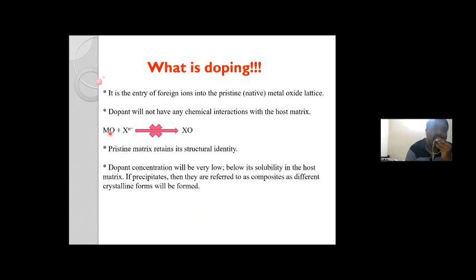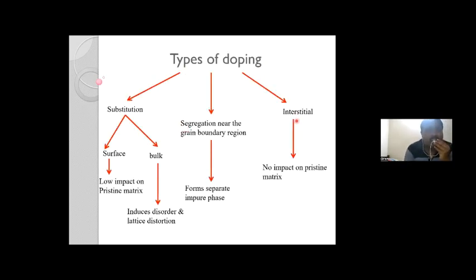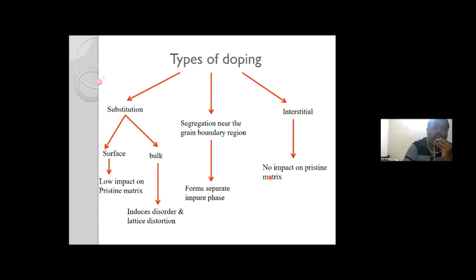For example, if zinc is substituting titanium dioxide, you get the impurity of zinc oxide. Interstitial doping happens with extremely small ions like lithium-plus, or when thermodynamic constraints exist for substitution. Interstitial doping will never have any impact on the crystalline matrix; interstitial sites are essentially voids.